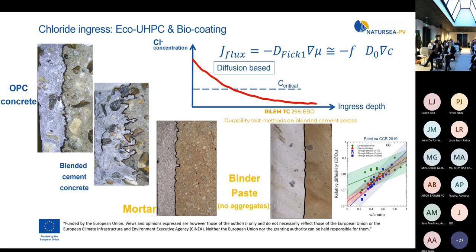Here I also wanted to mention that there is a RILEM TC on the durability methods of blended cement paste, so it really goes along with this, and we are reviewing the test methods there. On this picture, for example, this is just for the binder with different water cement ratios, which basically means more porous or less porous. Here it's called the relative diffusivity. That means how much lower the diffusion is than in a normal solution without pores.